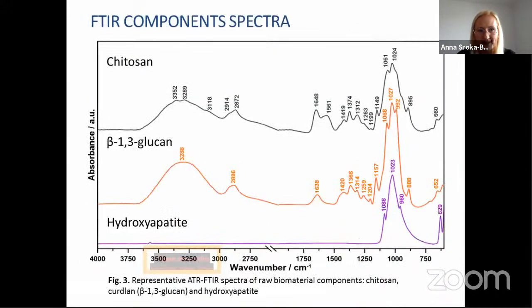So during that experiment, we used macro ATR FTIR imaging using the Golden Gate, the IMAC, which is the SPECAC accessory, connected with the macrochamber and FPA detector. That equipment was used at Imperial College London. So to present the first data, we first concentrate on the spectra of our pure materials, which were chitosan, beta-glucan, and hydroxyapatite.